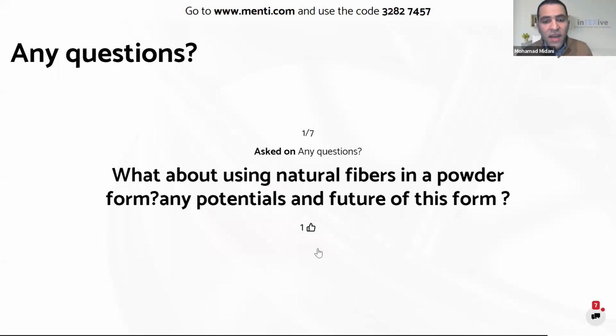The first reason, they have low aspect ratio, okay? And this is an important parameter in transferring the load from the matrix to the fiber. And natural fibers do not bond well with the matrix. Also, you have short fibers, so this is making things worse. But if you just want to substitute a certain percentage of the plastic with bio-based fibers, this is acceptable, but you will not get any enhancement in the performance.